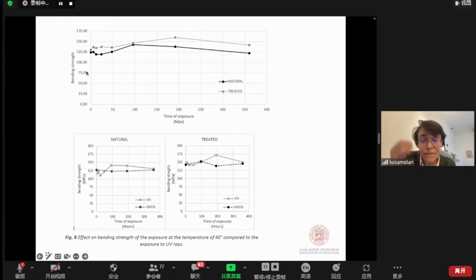These are the bending strengths, and what we saw is that the untreated sample, the natural one, basically had a slightly increasing strength and then a decrease. But after 360 hours, we do not see much difference in the bending strengths. Again, this is something related to the properties in the longitudinal direction, of course.